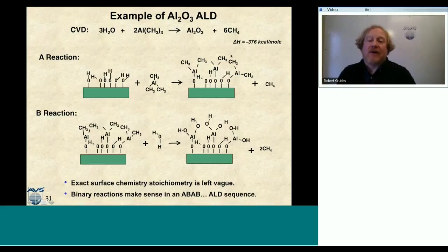Now we take that product surface in the A reaction and apply it to the reactive surface in the B reaction. And here I have this methyl terminated surface in the B reaction. I react that with water. I hydroxylate the surface. I remove all those methyl groups to make Al-O bonds again and methane gas. And so here we go. Again, we have the product surface of the B reaction is the reactive surface in the A reaction. And again, this enables us to run the AB-AB-like reaction sequence repeatedly to make a thin film grow.